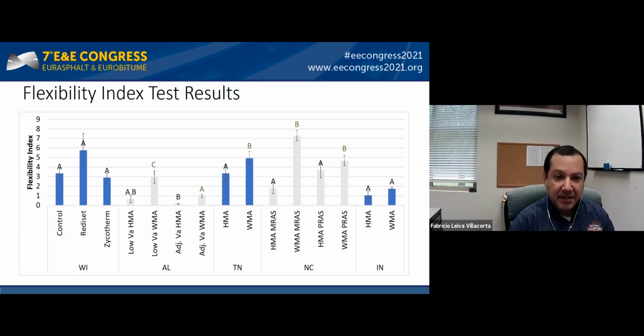And here's an example of flexibility index test results, where we were able to see for all the cases where the results were conducting the test on warm mix technologies, those results were better or similar. For instance, for the first one, Wisconsin, there was no statistically significant difference between the warm mix and the hot mix. But when you move to Alabama, Tennessee, North Carolina, those showed significant differences when going from the hot to warm mix. In at least 5 different pairs, we were able to see that the warm mix technologies outperform the hot mix technologies, which was good. We were looking for something similarly or better.